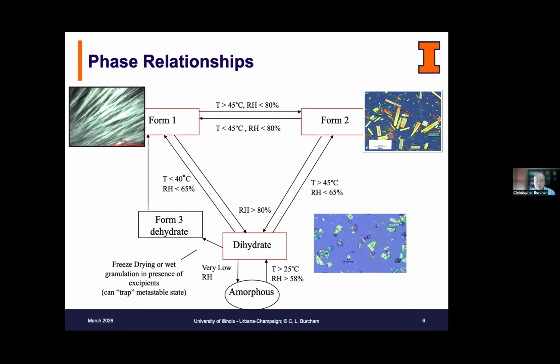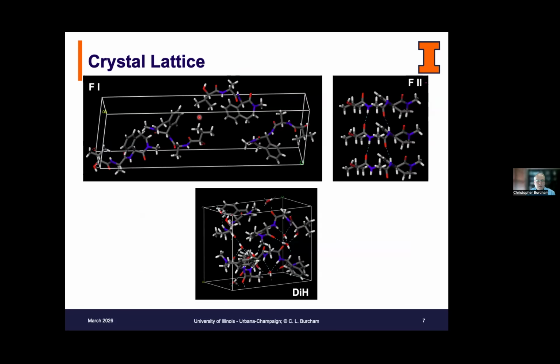We turned it to Form 2 because Form 2 had much more equant crystals, but there was much concern and consternation about choosing Form 2 as the target form, knowing that at room temperature it was not the thermodynamically most stable form. We could get over some of that anxiety by looking at the conformation of the molecules in the